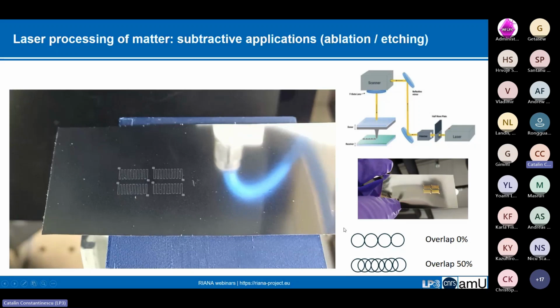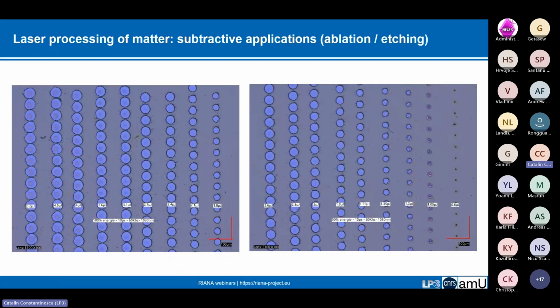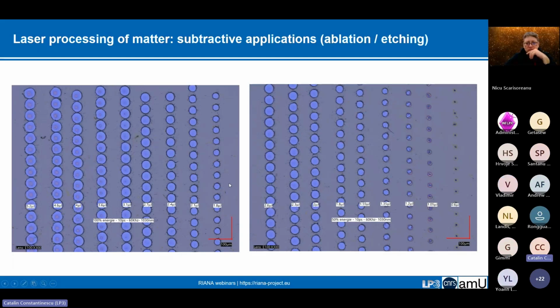So the best part of this setup, the synergy behind it, is that we can use it to print such structures, but also to etch. Printing and etching basically take the same time. So it's a very fast process. Now I'm just showing how etching of a multi-layer structure can take place by controlling the fluence. By controlling the fluence, we can control the size of the ablated material, the actual depth that we can achieve, and again by adjusting the overlap, by controlling the surface quality, we can control the uniformity of the structure.